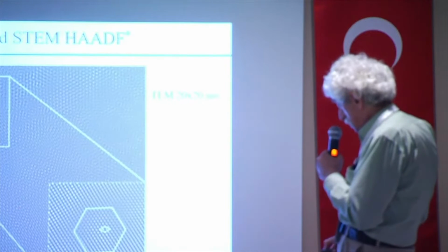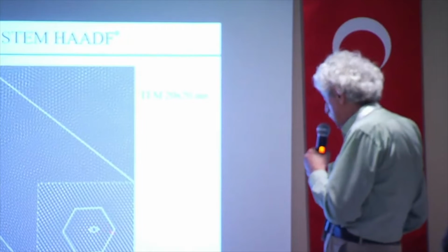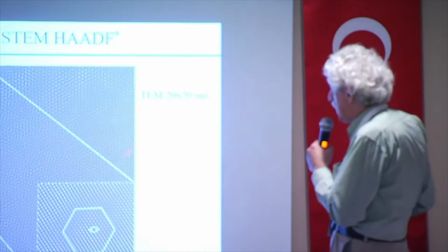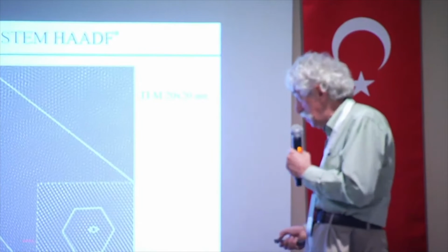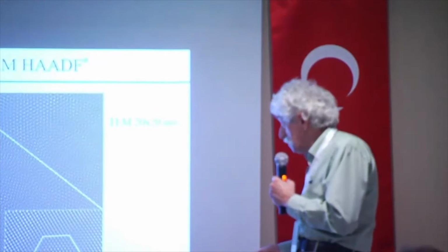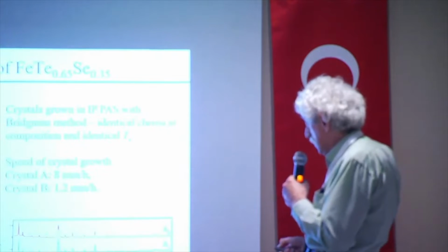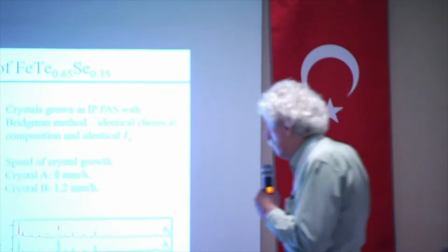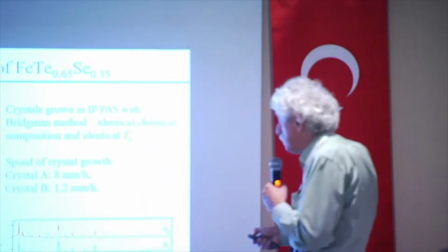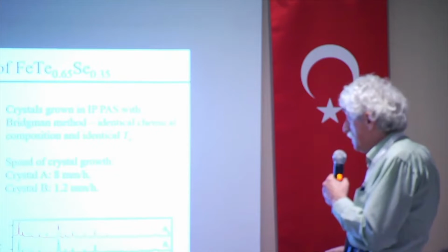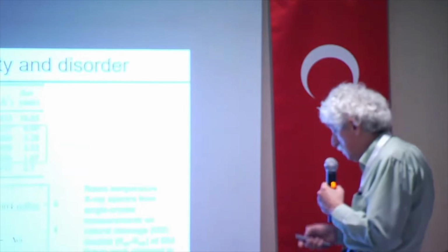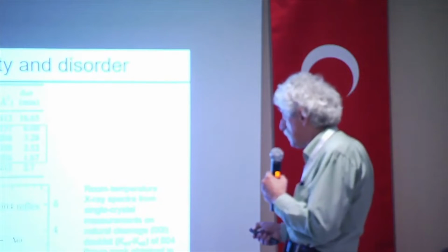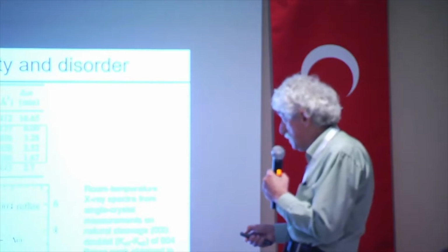What does it mean? Basically, you have the situation like this: you have a tetragonal host lattice, and in this tetragonal host lattice, some hexagonal areas appear. This means that this crystal is not perfect. And if you grow single crystals, you can play with the speed of growing of crystals, and then you can get a slightly different X-ray diffraction picture. Here is an example of several crystals which were grown with a different speed, and the difference between them is the width of this peak